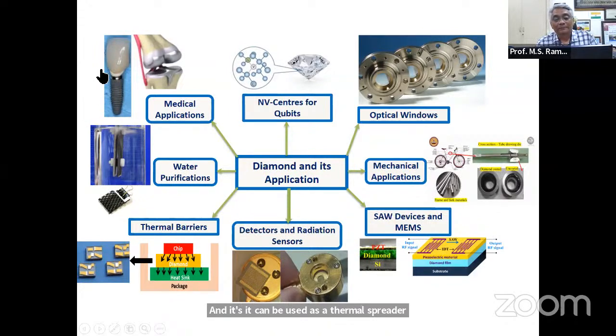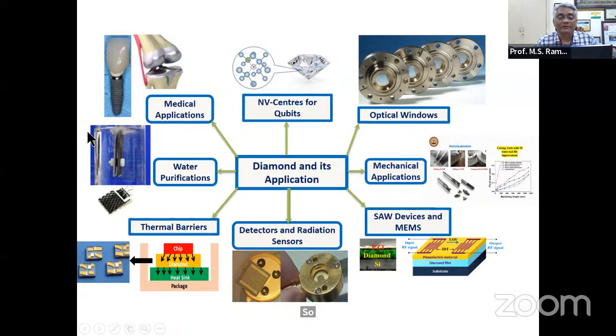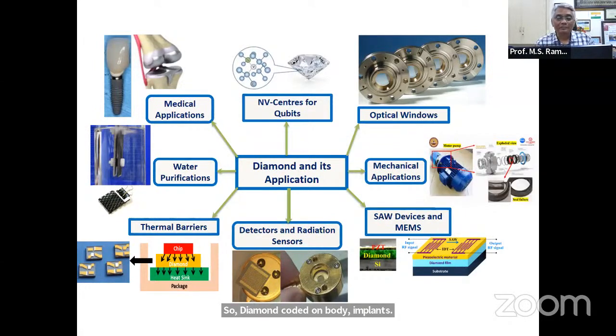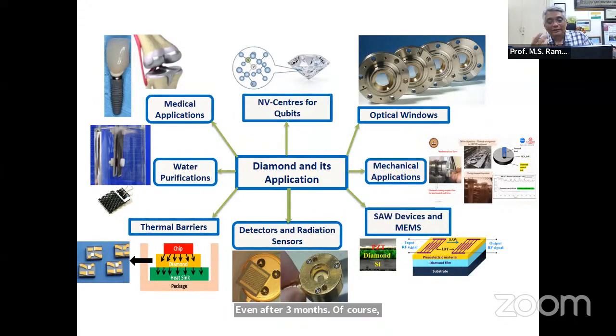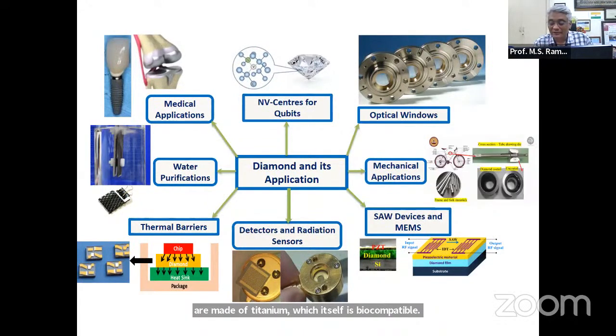So with diamond coated on body implants, we showed that there is no bacteria formation even after 3 months. Of course, these dental implants are made of titanium, which itself is biocompatible, but diamond coatings are required to further enhance the longevity of these coatings.